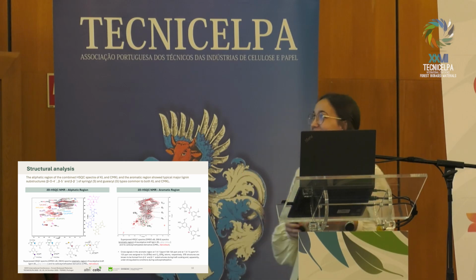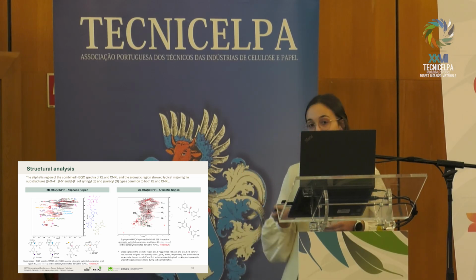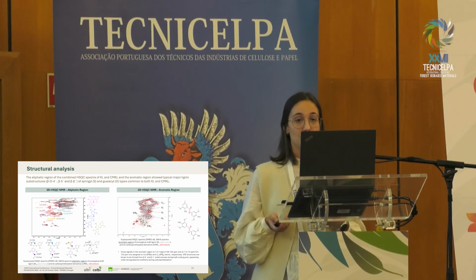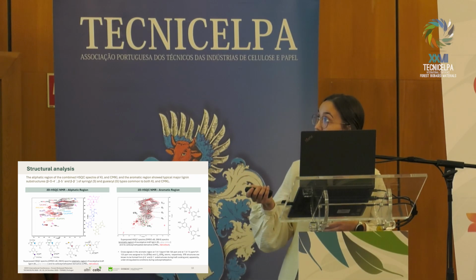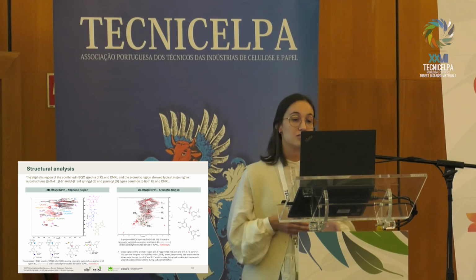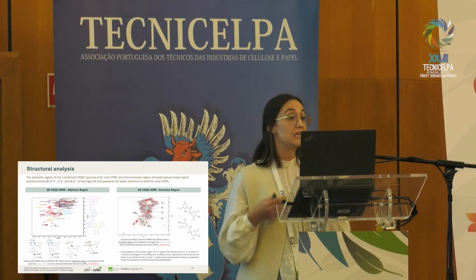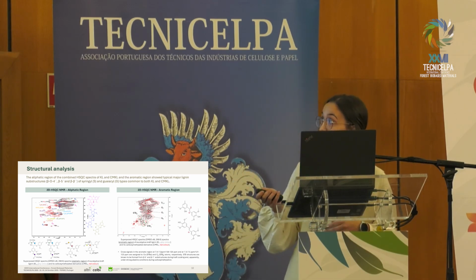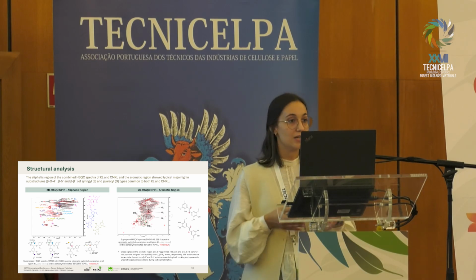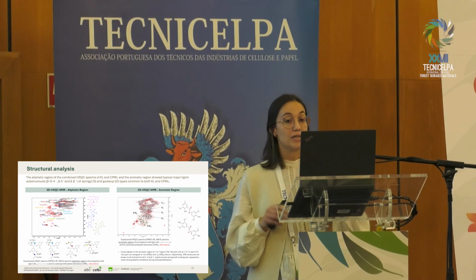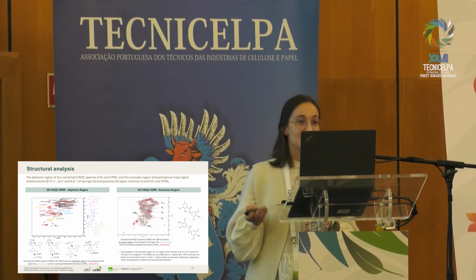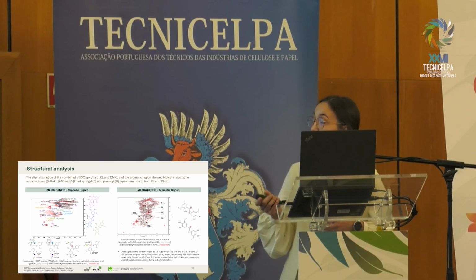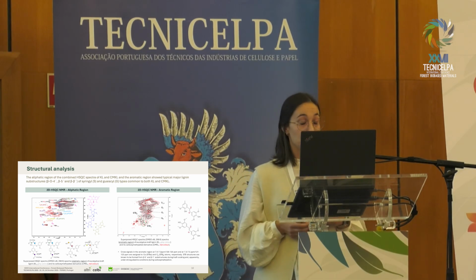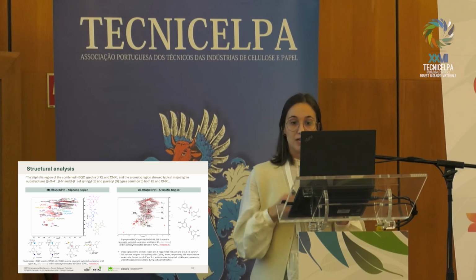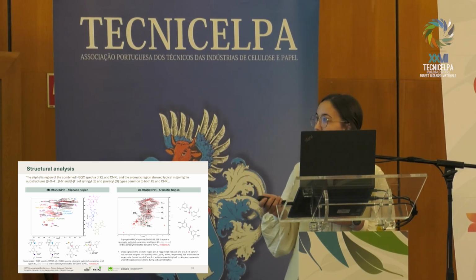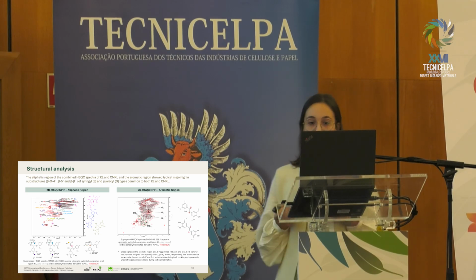We also analyzed the proton and carbon NMRs, and regarding the proton NMRs, we observed that new signals appear for the carboxymethylated kraft lignin at this red band, which are associated to the methylene protons in carboxymethylene phenyl ethers. Additionally, increased resonances at this orange band indicate the presence of methylene protons in carboxymethylene alkyl ethers. Quantitative analysis using phenolic methoxyl groups as internal standard showed a decrease in the phenolic hydroxyls of about 40% and in aliphatic hydroxyls of about 80%.